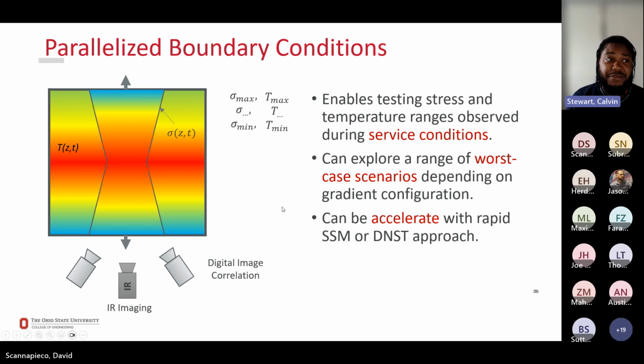Now, we could even take this a step further. Instead of doing delta sigma and delta T independently, we could also combine those together, where we have a sample with a gradient shape and a gradient temperature field. Now that enables us to do tests that are more like service-like conditions, where depending on how we design where these gradients are, we can literally have a test that has multiple worst-case scenarios for our actual performance part.